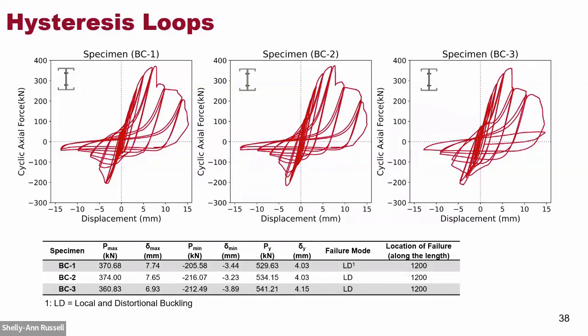So after testing of these specimens at the lab, we observed this behavior for 3 specimens with various fastener spacings for the C sections. The behavior was asymmetric pinching material behavior. After local buckling happened, the stiffness and the strength degraded significantly after this point, but in tension, it was still continuously working in the tension area. So I will discuss this point in the next slide.